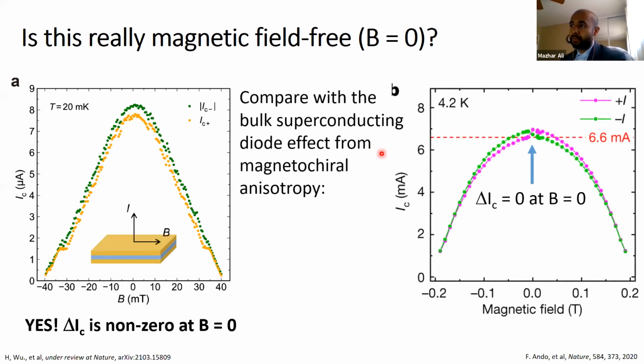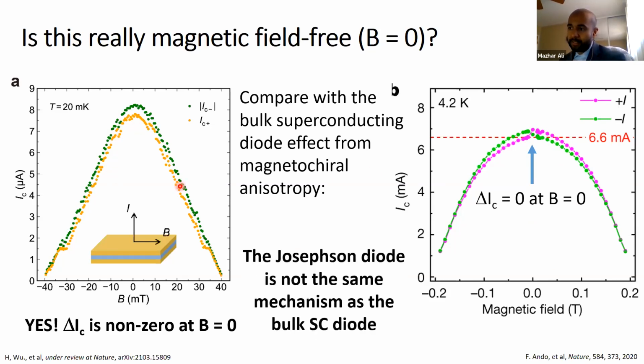But to finish the comparison with the magnetochiral anisotropy route, this is how the magnetic field dependence of IC looks like. Exactly like we derived earlier, precisely at zero magnetic field, you must have a zero delta IC. It can exist. In fact, it's maximized with a small magnetic field that also then gets suppressed, but the I plus and I minus cross at B equals 0. So you can just see very clearly it's not the same. So the Josephson diode is definitely not the same mechanism.